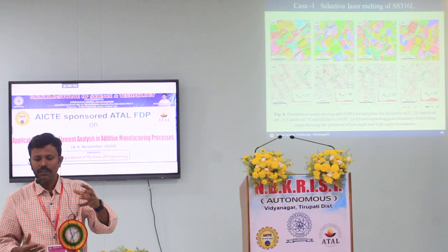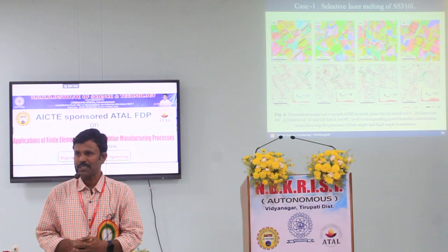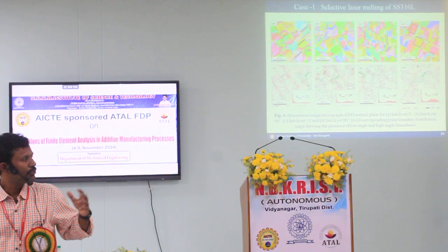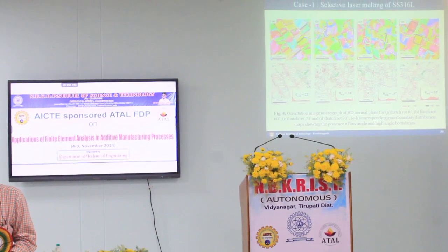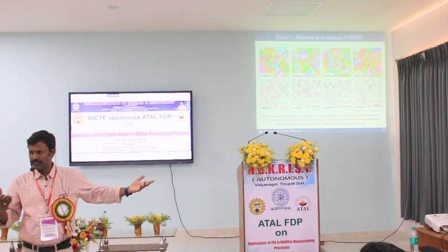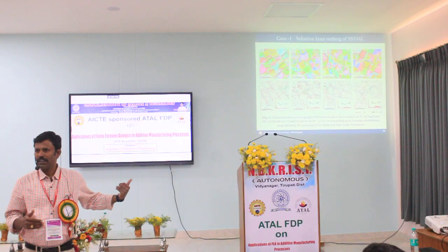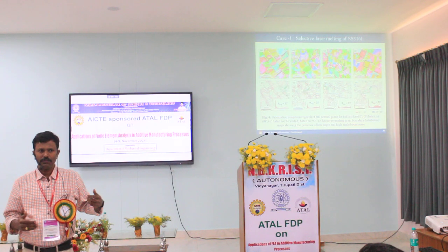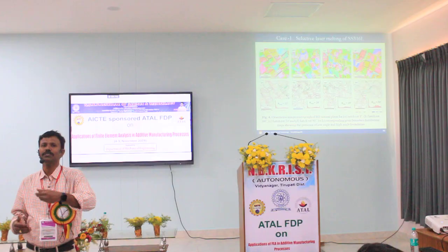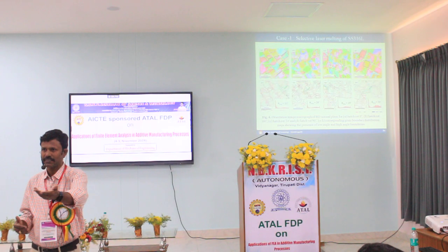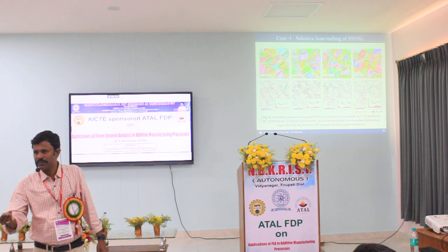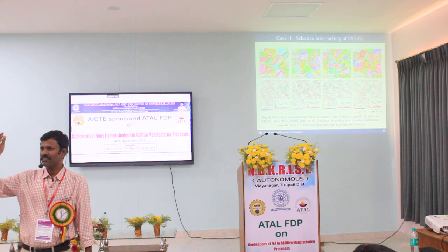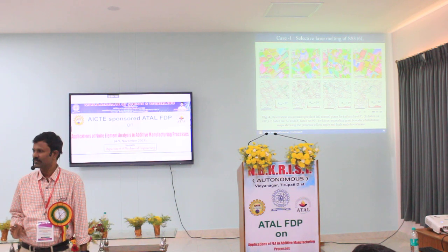In depositions during additive manufacturing, especially titanium alloys, you will get this huge difference. If you vary the laser power to a smaller extent, suddenly the green lines will increase, or if you increase it, the red lines will increase. With a minor fraction, say a 5% to 8% variation in red line increase, you will sacrifice properties. To what extent? Not just 10 or 15 megapascal. It is like 500 coming down to 300.